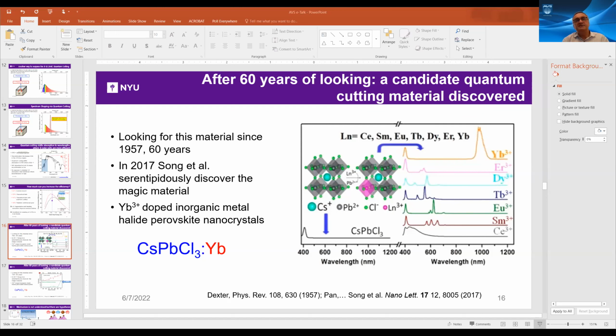What if the Tb3+ ytterbium 3+ couple was used instead of the double couple? One can try. That's not something I would try, because one of the things that I talked about with ytterbium 3+ is that it has only two levels. So there is only one transition that the energy can couple to. When you go down to the other lanthanides, the energy diagram is a zoo. So you'll couple the energy into various different emissions. If one is trying to get broadband emission, that's great, but that's more for light emitting diodes and light emission. For this particular application, I think ytterbium is it.